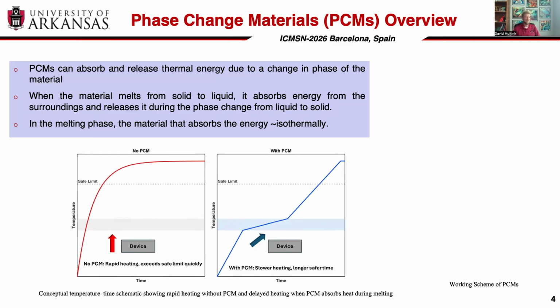So a phase change material essentially is something that undergoes a phase transformation, and that phase transformation happens isothermally or essentially isothermally, where you have energy absorption through that phase change that is controlling the local temperature as that energy exchange is taking place. So where you might see a temperature rise that goes above the safe limit without some sort of latent heat incorporation, that incorporation of phase change can delay that event so that you have more time to respond to the thermal event in your system.